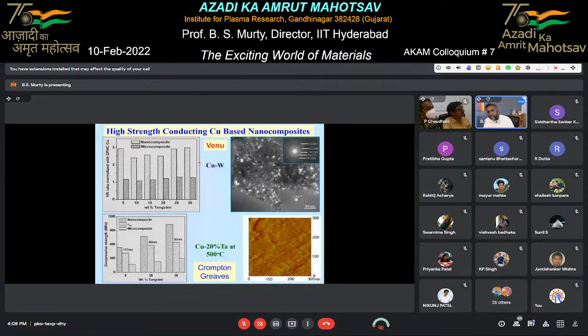We can also make functional materials. This is copper. Somebody from Crompton Greaves asked us, do you have a way by which I can make copper very strong? Because they use copper as a good conductor, but copper is very soft. We said we can make copper into nano and then make it very strong. At the same time, to ensure this nano copper remains nano copper after sintering, we add some amount of tungsten, tantalum, things like that. When you add them, they go to the grain boundaries and pin the grain boundaries of this copper so that the material retains its nanostructure even after sintering.